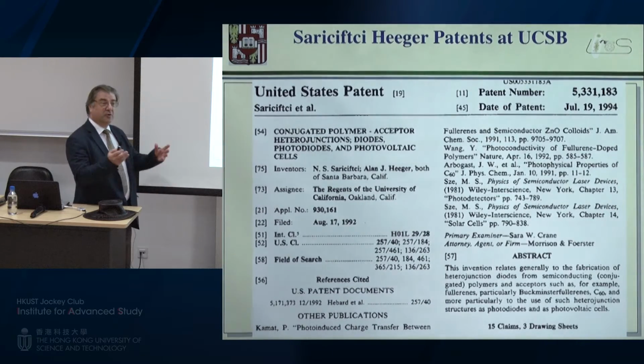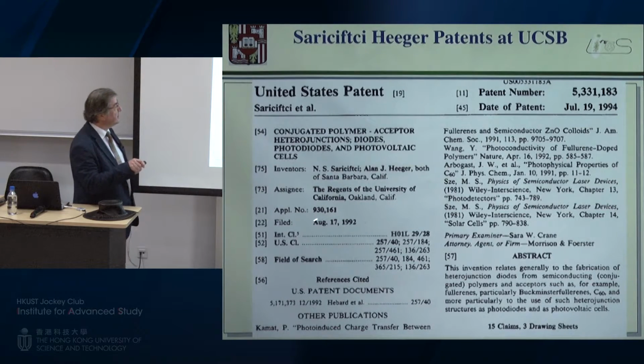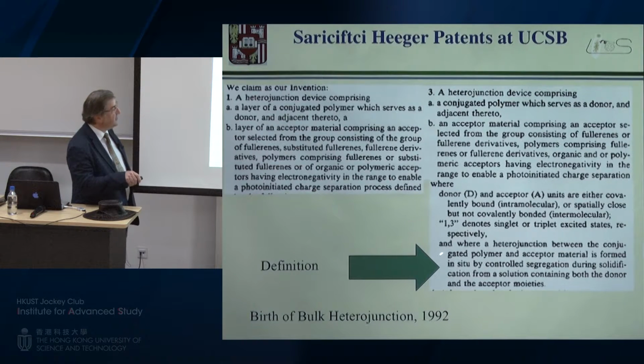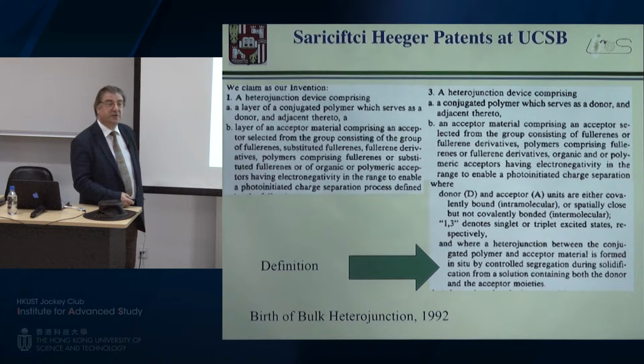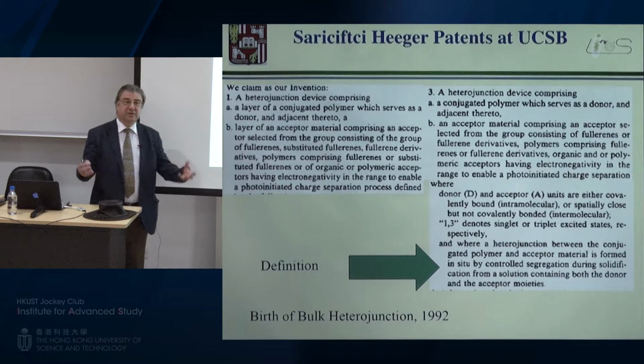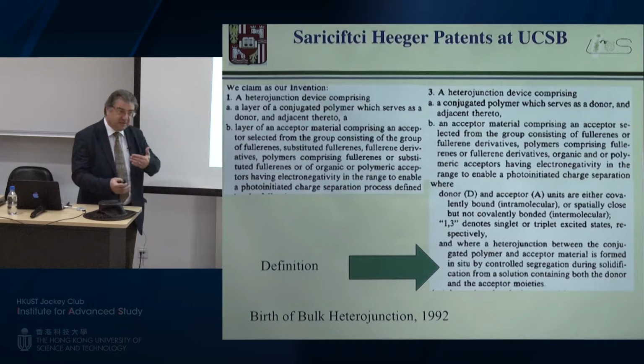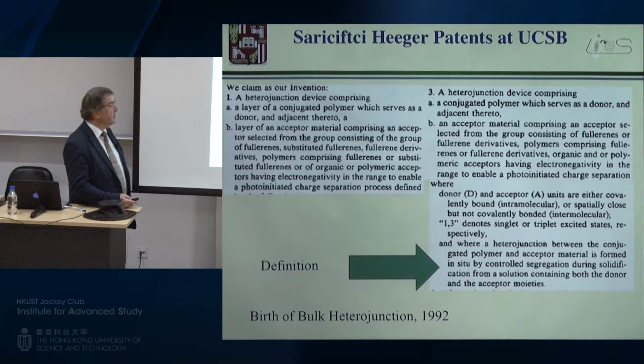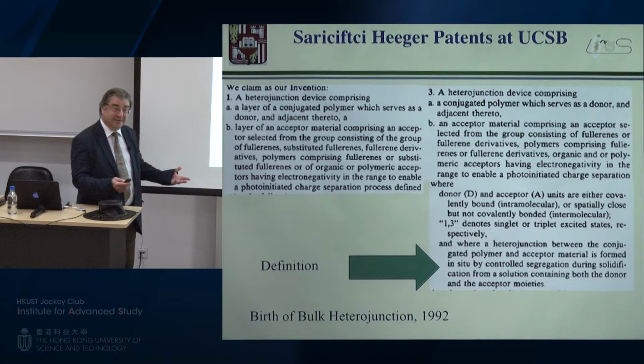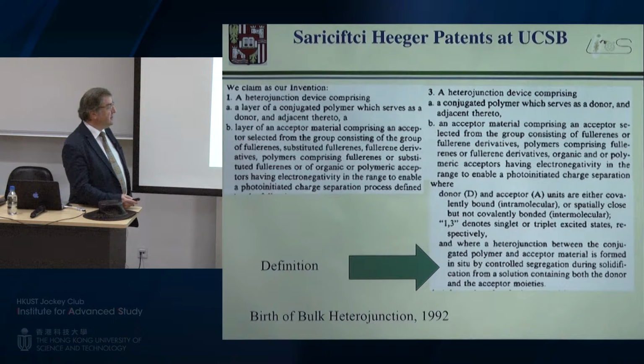So, talking about patents, we also had a patent. This is August 92. And in this patent, we actually describe the definition of a bulk heterojunction as a heterojunction between the polymers and acceptor materials formed in situ by controlled segregation during solidification from a solution containing both the donor and acceptor moieties. So basically, you mix these two solutions and cast one single layer from one solution, and hope for the best that it really phase separates into a nice system. So this was actually the definition of the heterojunction.